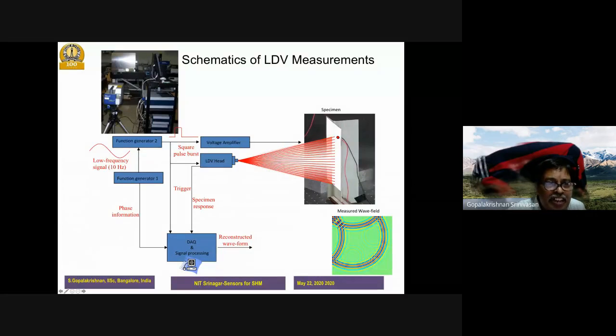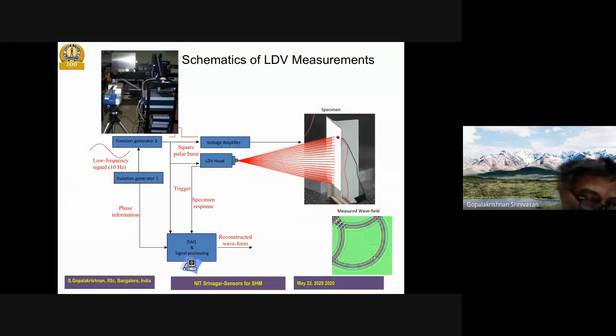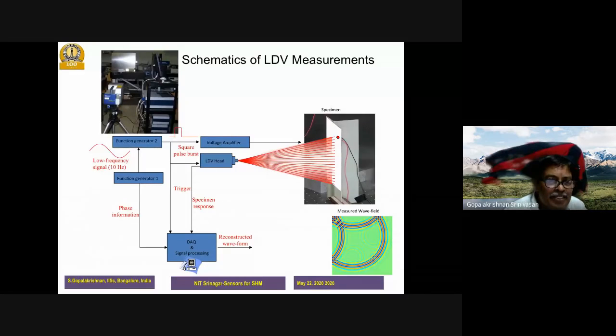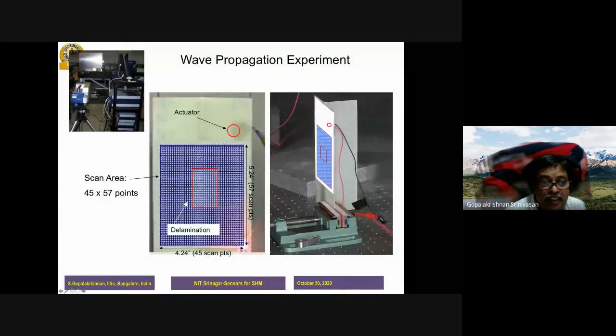So you choose the area where you want to monitor, and that area is pixelized. At each pixel point, you will get the response. So you have a seamless response all over, and you can use all the techniques you have to pinpoint where exactly you need. Okay, so this is the principle. You have a function generator, you have a laser head, this is a piezoelectric, it points, and the complete wave field is measured. The camera chooses the region where you want to measure, and each region is pixelized. At every pixel point, I get the response.